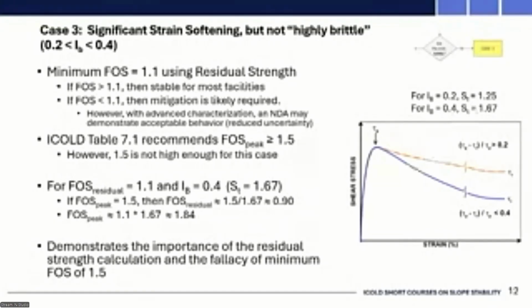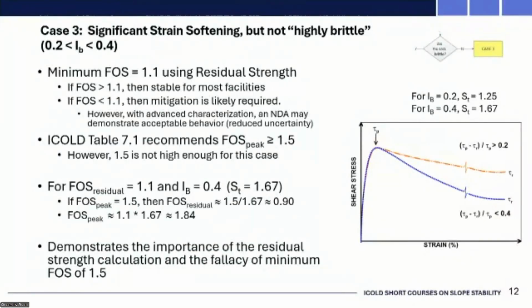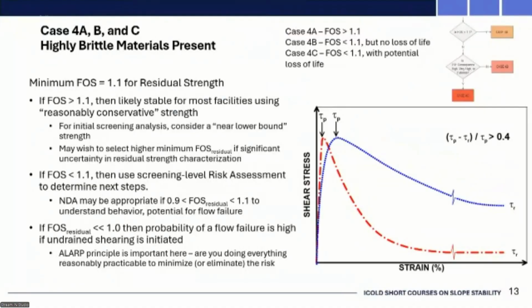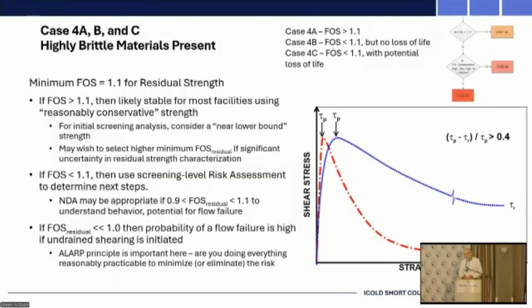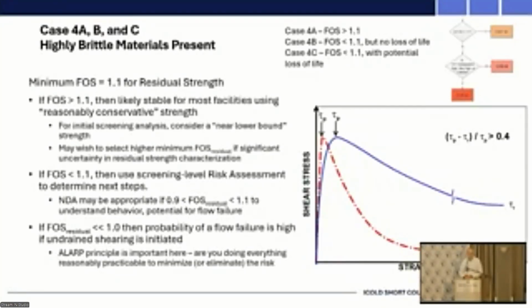And this is again where I've had these arguments with people that are way smarter than me, but I think they kind of get lost in taking a very hard, adamant position that we must have a factor of safety of 1.5, when the 1.5 is not always going to be adequate if you have brittle conditions. And so moving on to case 4, where you have a brittleness index greater than 0.4, or greater than 40% strength loss. I have in previous analyses gone through the same type of analysis, that if you have a brittleness index of 0.8, you may need a factor of safety for peak conditions greater than 4.